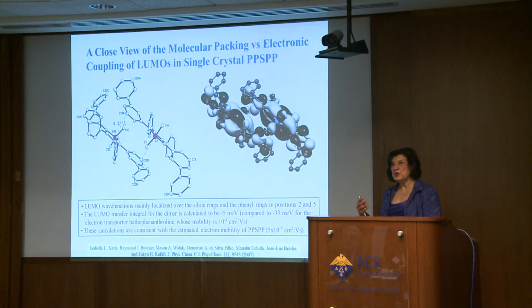And we compared that to one of the good electron transporters, called bathophenanthroline, which has a transfer integral of about minus 35 meV. And from there, we were able to determine the electron mobility of this compound.